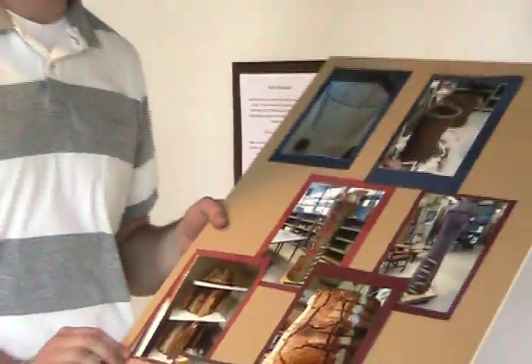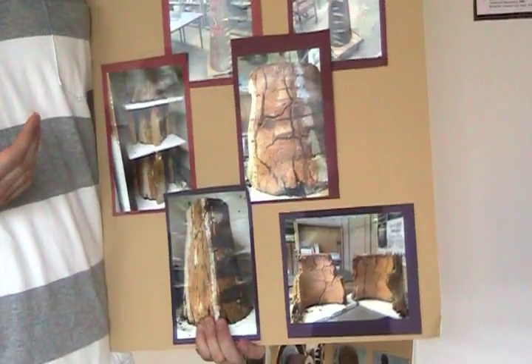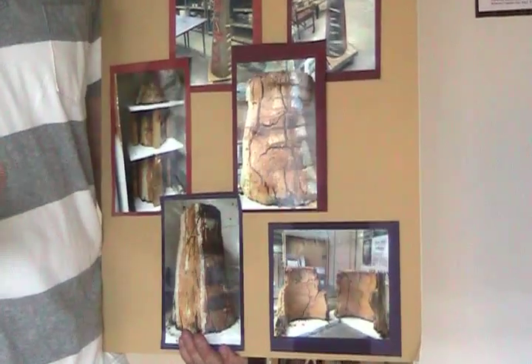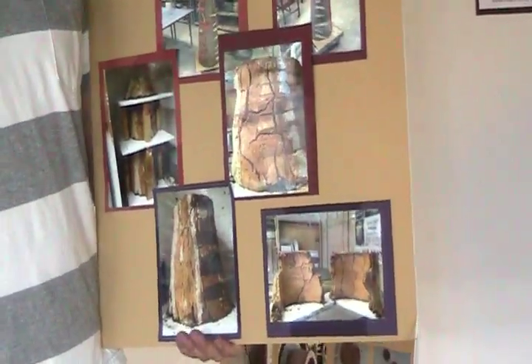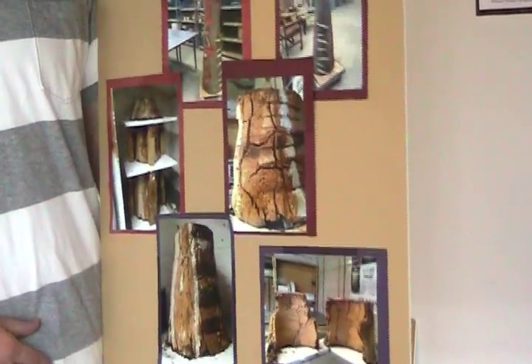With that, I created tomato cage forms, made roughly a six and a half foot sculpture, and put it into a kiln to heat up at around 2300 degrees. Pulled it out of the kiln — the results visually I loved. They had the texture, they had the ceramic surfaces that I like to achieve, but the forms crumbled and I was left with shards because the armature melted at a lower temperature than what I fired the kiln to.